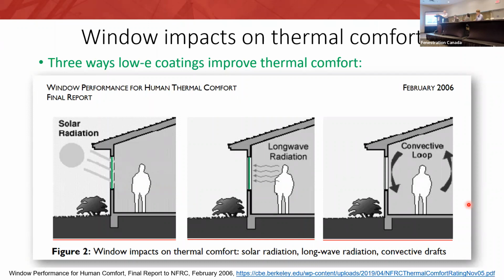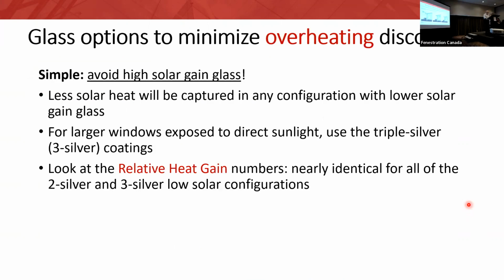And all the low E coatings, high or low solar, do a great job of keeping the long wave radiation in your home. Once you've heated your home, whether by the sun or your heating system, it's there. The third one is convection. If you have a cold glass surface temperature, then you've got a kind of convective loop going and a draft in front of your window. And if you put in a low solar coating, well, actually any coating that will warm the glass surface. So in other words, not a room side coating, but an internal coating, that indoor glass surface temperature will be warmer. It will break the convective loop and lead to greater comfort.